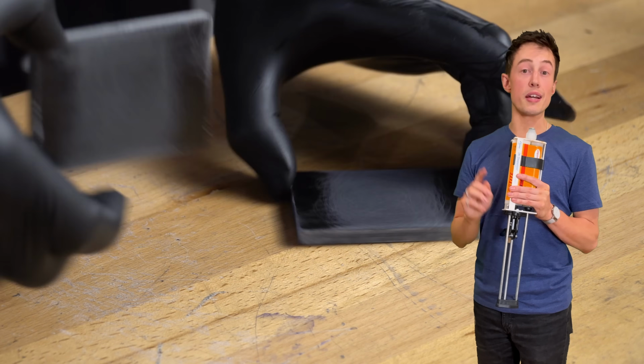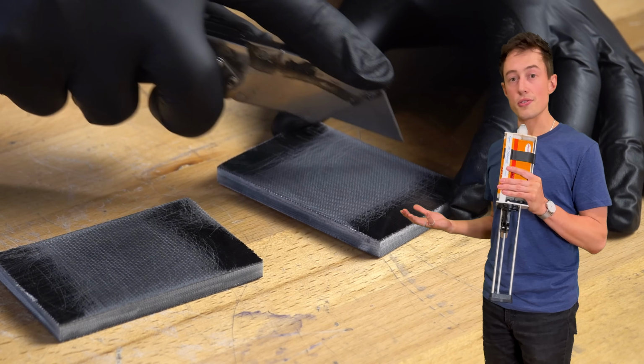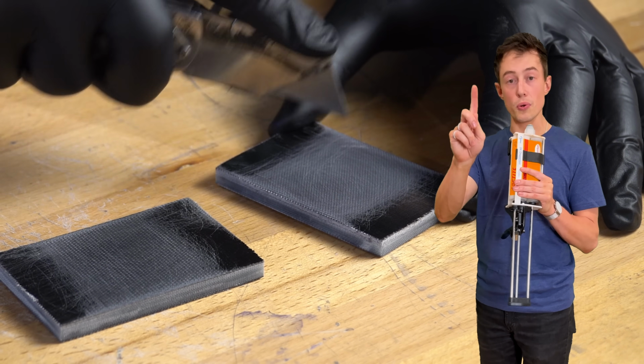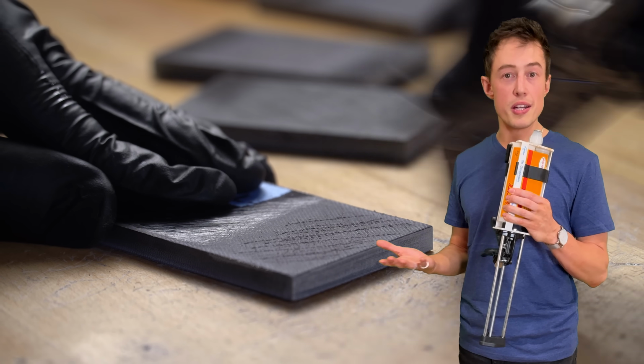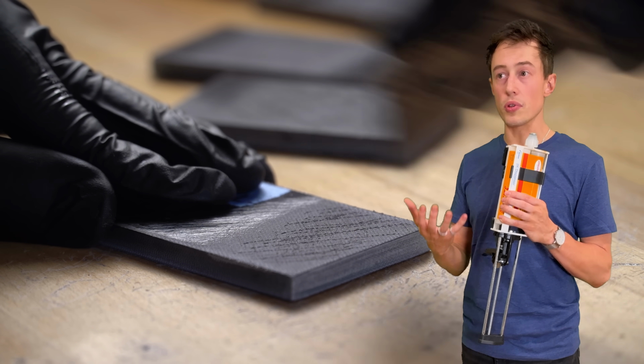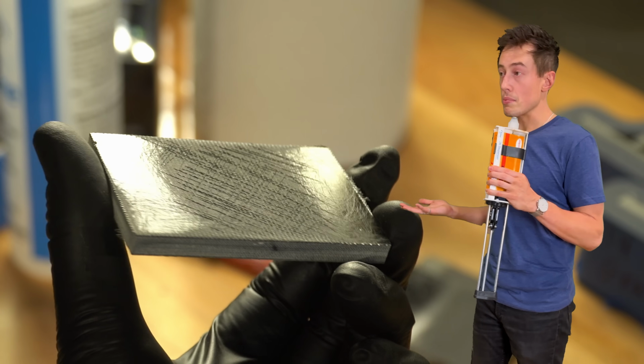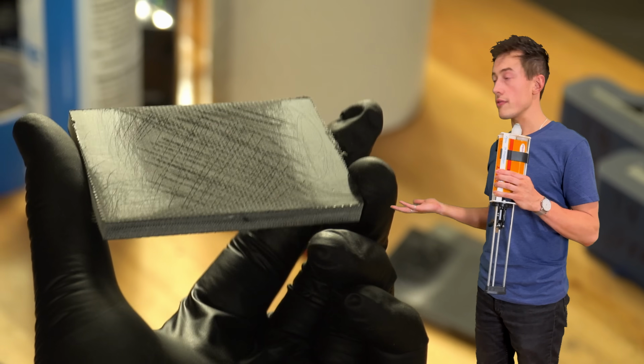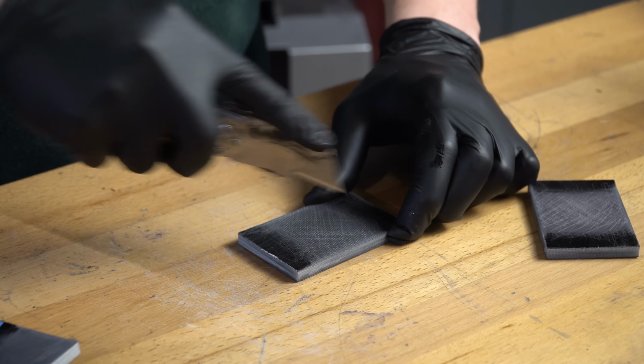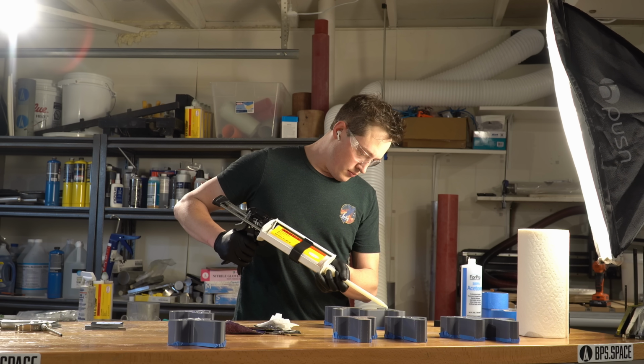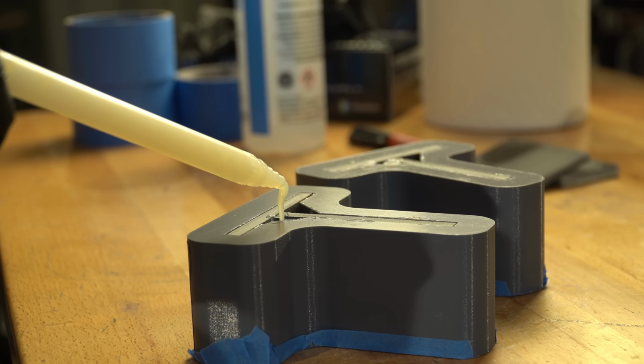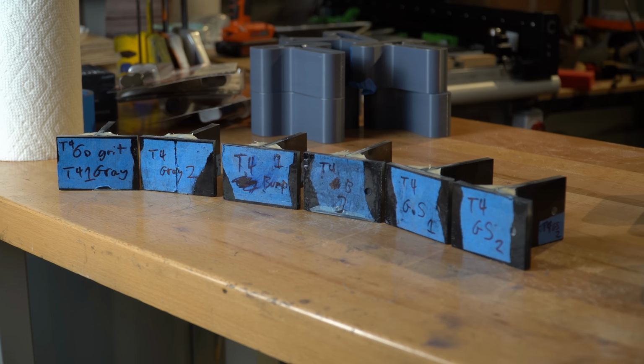The third set was sanded like the first. I sanded using moderate pressure until the piece was gray, but then I scored it with a knife. Maybe by allowing the epoxy to seep deeper into these grooves, we'll get a higher bond strength. Low grit sandpaper seems to perform well, so what if we just rough up the surface even further? For each of these samples, after cleaning with IPA, I pushed epoxy directly through the mix nozzle into the mold. Then I let them cure for 48 hours, and now let's break them.